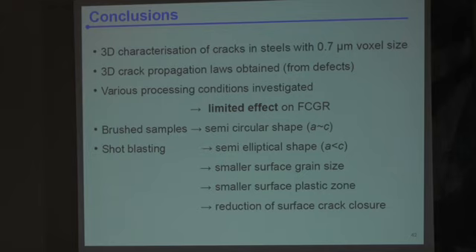But apart from this effect, which is, I must say, not so big, we found that there was very limited effect on the crack growth rate of the small cracks from the different forging conditions that we investigated.